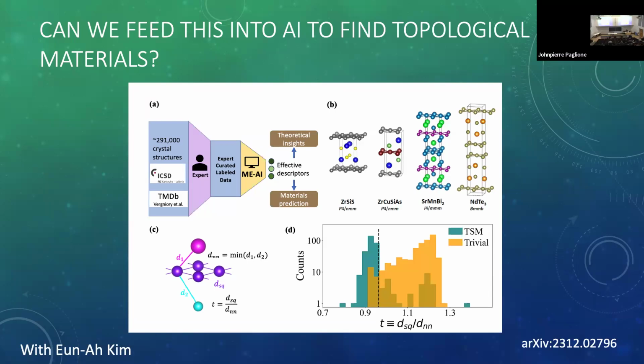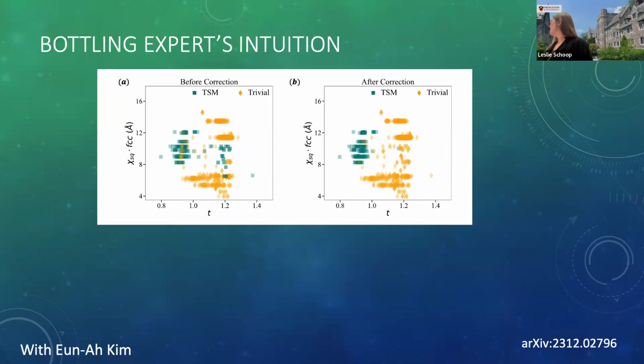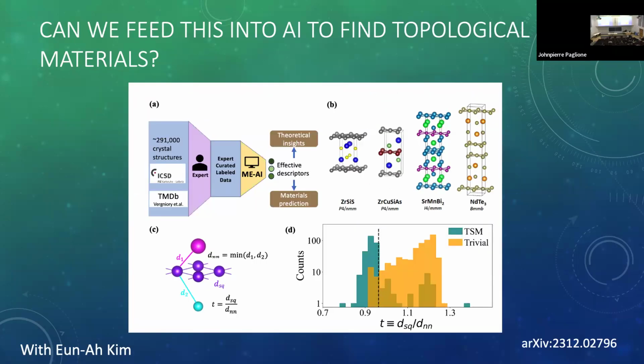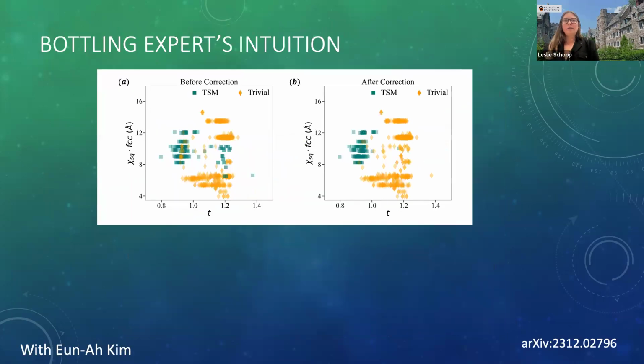And then this is how the data is separated by the tolerance factor that we found, our distance ratio. You see it does separate the topological semimetals from the trivials, but not as well as we originally thought. We worked with a smaller data set in our paper, so you see we have some wrong entries here. So we're trying to see if AI can recover this. We didn't tell the AI about this ratio, but also whether it can find more parameters to distinguish the topological semimetals from the trivial materials. And so it did.